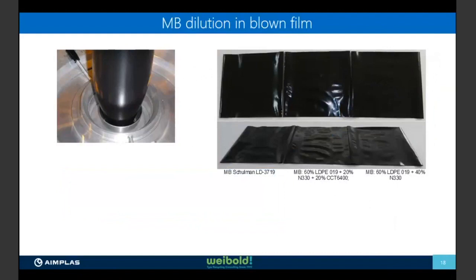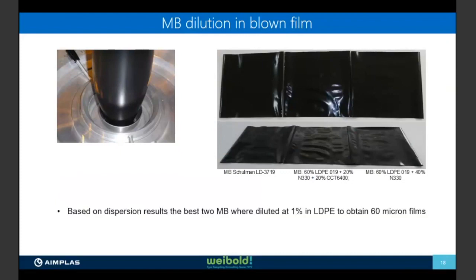Here we made the trials in film, and here you can see down this specimen, you will see the different formulas. And what we did, first of all, we did some visual analysis, and we can see, besides processing, that was perfect, we obtained very nice films. And here you can see that it's quite complicated to find the difference between them. Okay, so that gives us a good idea of how good were the three compounds that we were comparing. We mixed at 1% and we obtained 60 micron films.